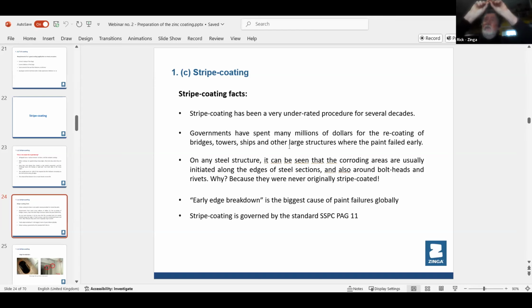And stripe coating is all the areas where it breaks down. And of course, with paint, if it breaks down in one area, the atmospheric moisture gets underneath every night and starts creeping. It goes underneath the paint and the rusting, and the paint starts lifting off and blistering. It isn't like Zinga, where you can have damage, but because of the throw, it's still protecting the steel everywhere. So even with damaged areas, it will not corrode. It just sits there. But with paint, if it's damaged,